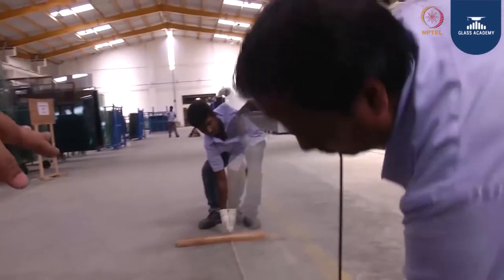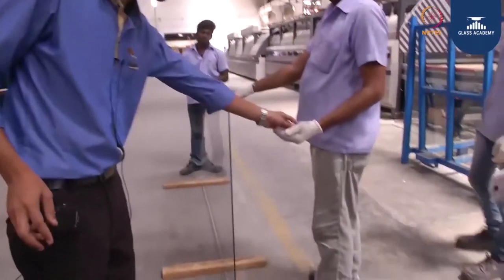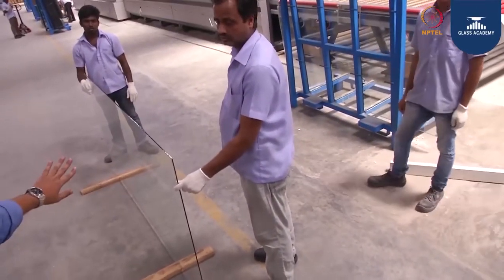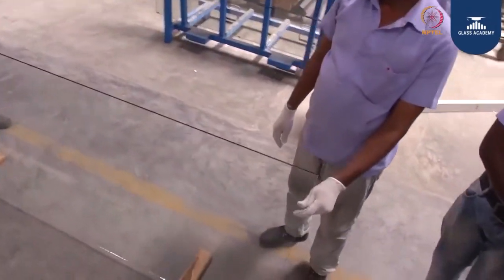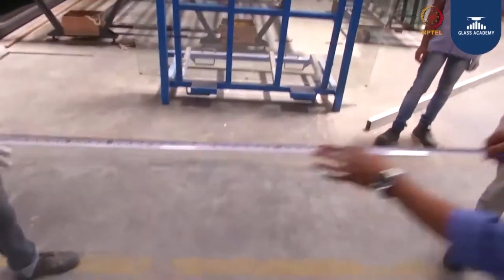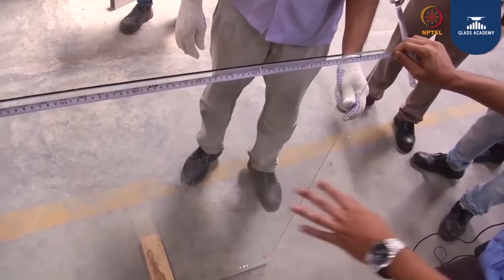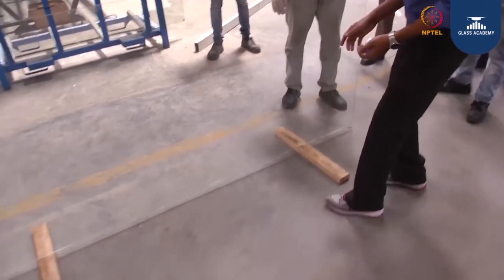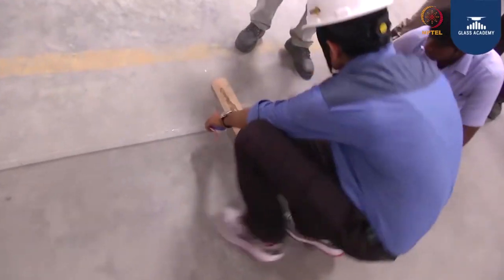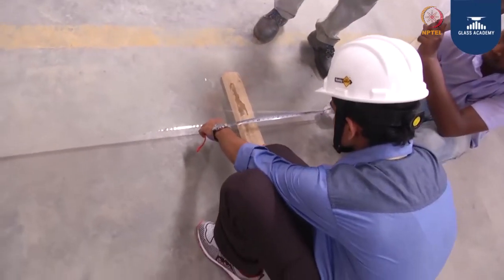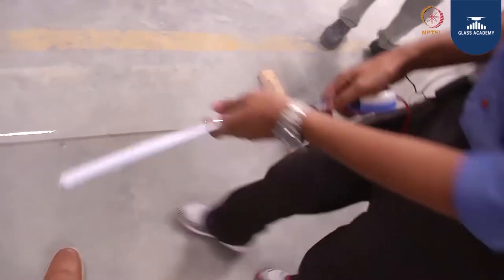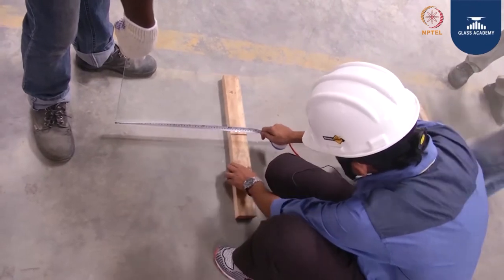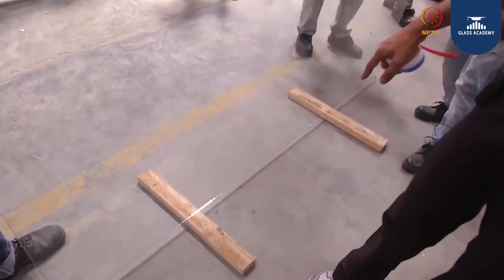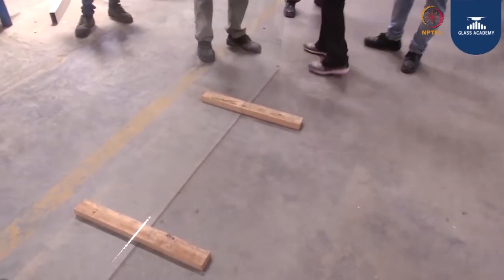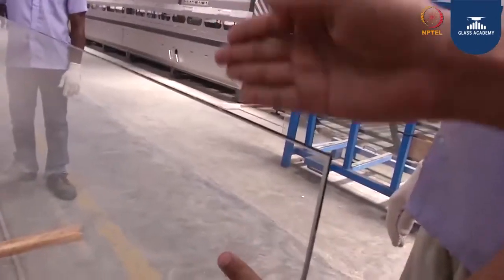Now we are going to measure the bend in the heat treated glass. First we need to measure the bend, which should be always measured on the longest side. So it is 2100. So next we need to apply setting blocks at the quarter positions. So what we are doing is we are giving setting blocks at 500 distance. Now visually we need to see the bend direction. Next step is we need to see visually where the bend is. So it is towards this side.